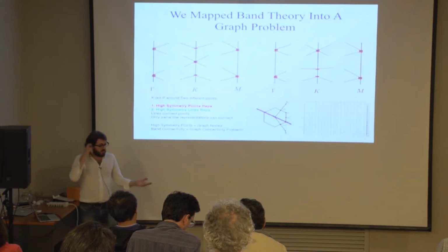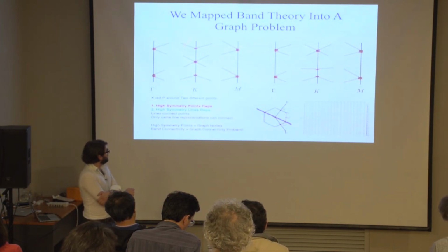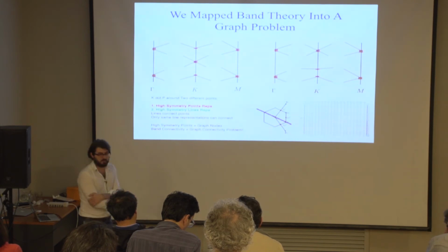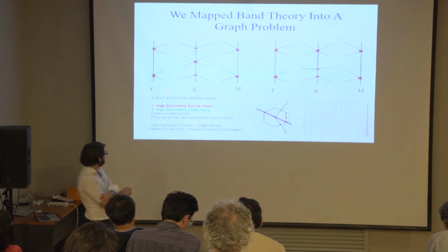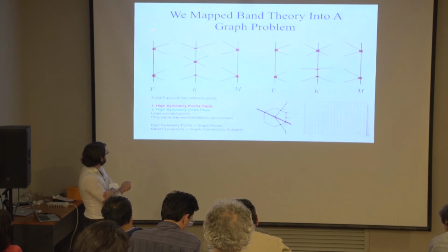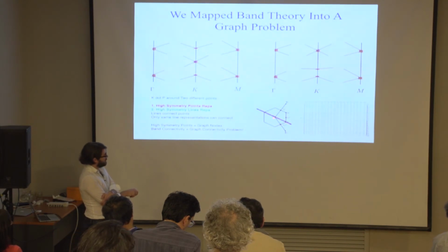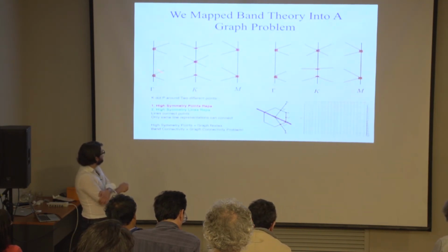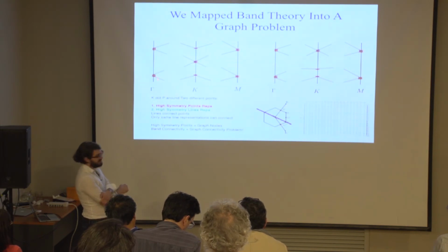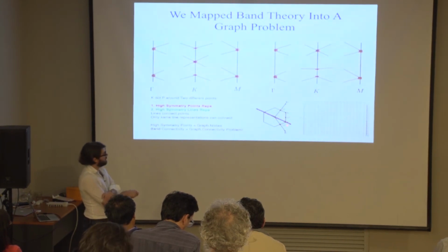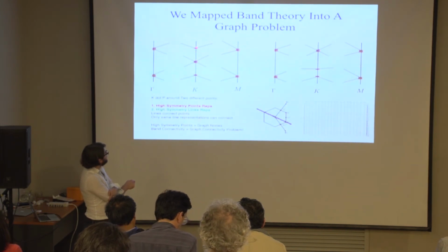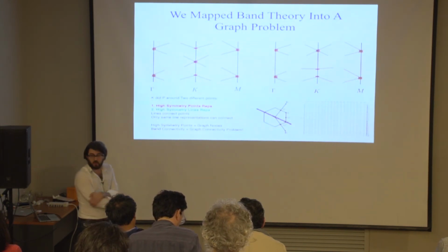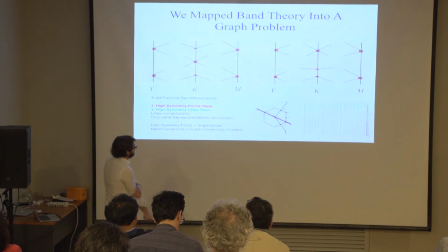So with that, we can find out the possible connectivities of bands in the Brillouin zone in the following way. So this is for the graphene example that I gave before. These, in red, are high symmetry points. So gamma, let's just focus on gamma and K. And at these high symmetry points with spin-orbit coupling, the gamma representations are always two-dimensional because I have Kramers. K is not a Kramers invariant point, so I can have one-dimensional representations, and indeed I have. And the representations are two one-dimensional and one two-dimensional of C3v, etc.